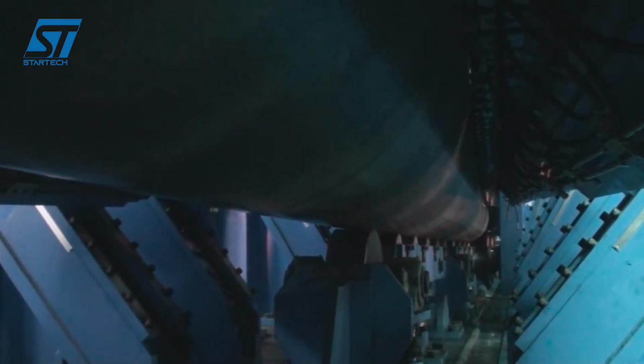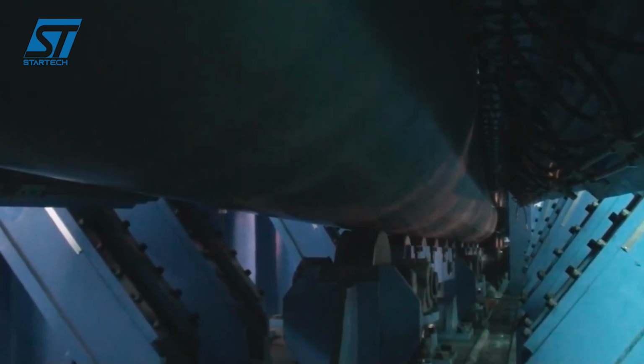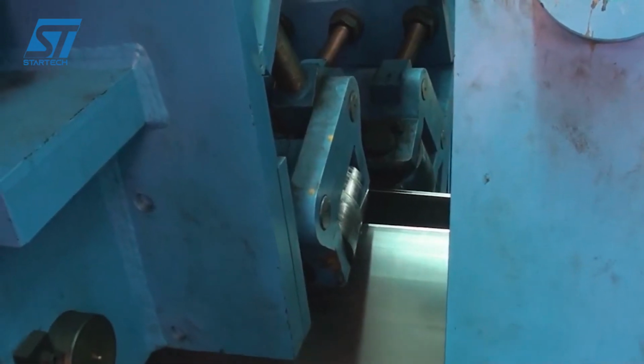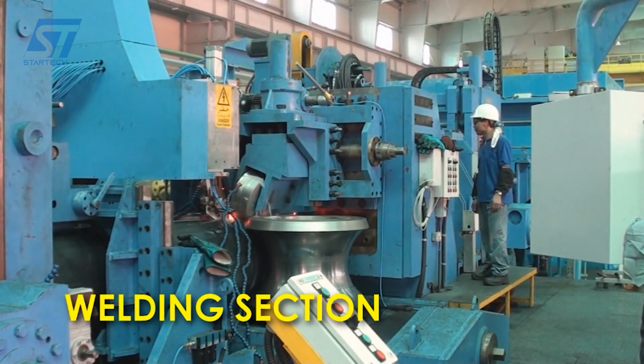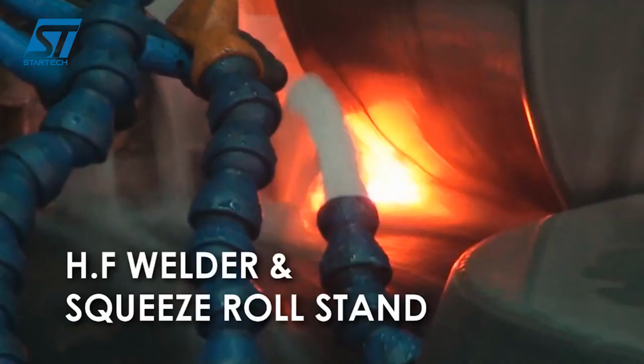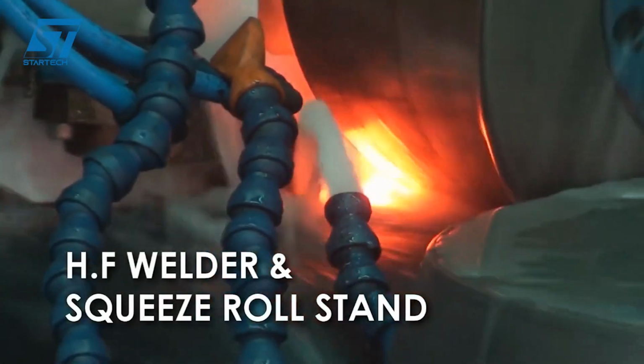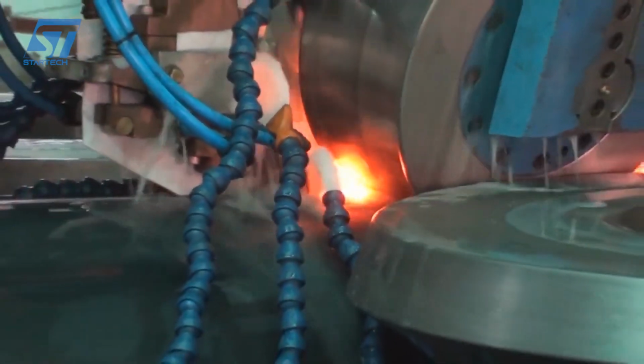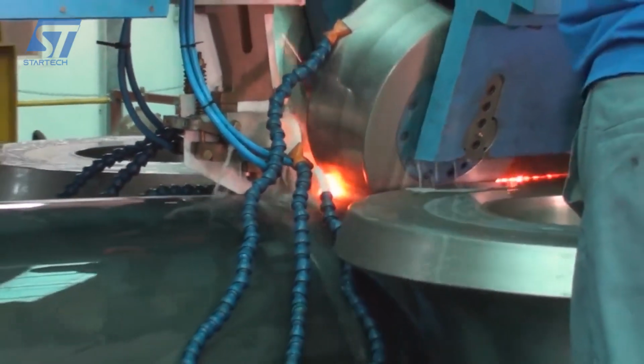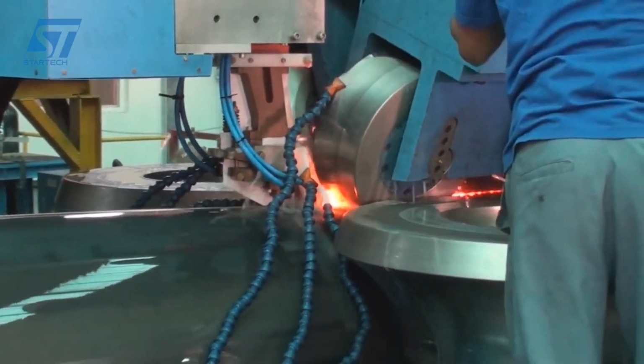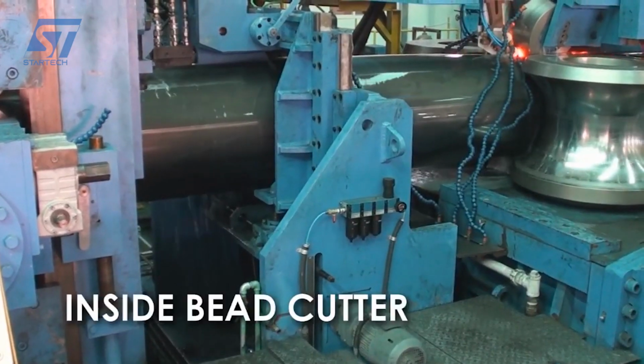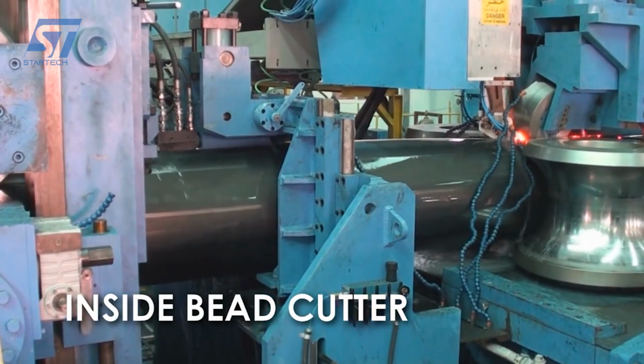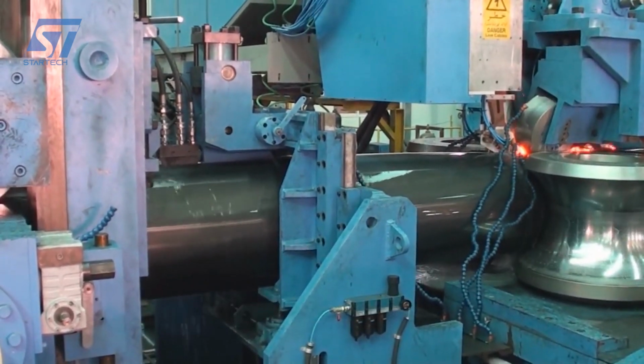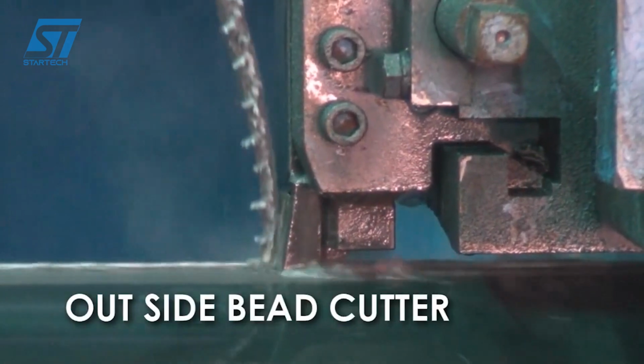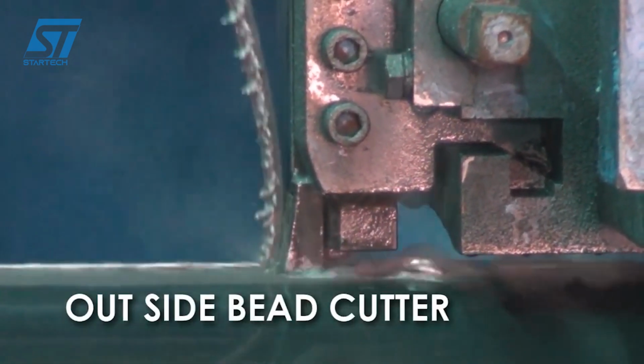This system is particularly effective when producing tubes with high diameter to wall thickness D/T ratios from 40:1 to 100:1, i.e. tubes with thin walls compared to their diameter. This is a major challenge for traditional methods due to the risk of distortion and wrinkling. Because the forming process is gentle and continuous, the system minimizes the impact force on the material and tool, thereby reducing wear and extending the life of the tool. With continuous forming, it allows for higher productivity than traditional methods. The system helps to produce tubes with precise shapes, smooth surfaces, and little distortion.